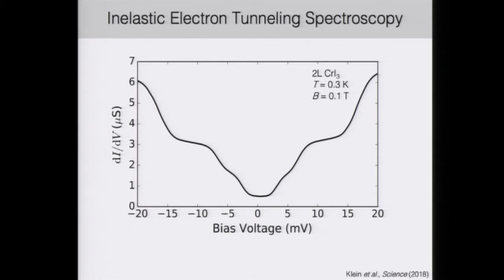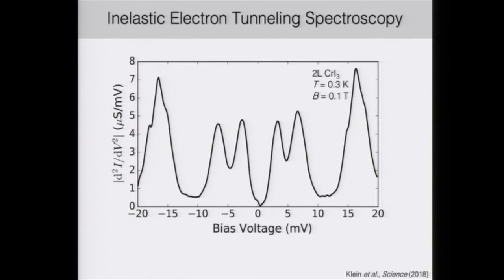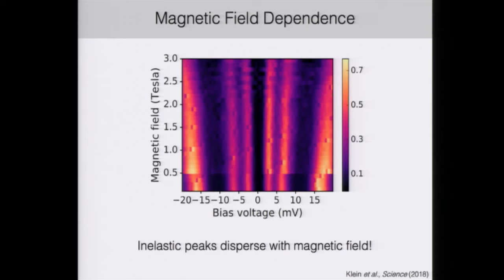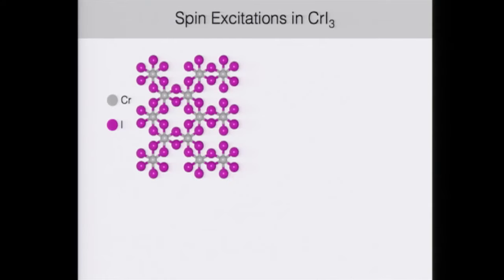We see these little features that, if you take the derivative of the data, you can see emerging much more strongly as peaks. And what's more interesting is that when we looked at how these peaks evolved in a magnetic field, we see that they seem to be dispersing somewhat linearly with the magnetic field. In order to understand these better, we can think of what happens to the spin excitations in chromium iodide. So if we start with a monolayer of chromium iodide, since the moments are localized on the chromium sites, we can ignore the iodine.